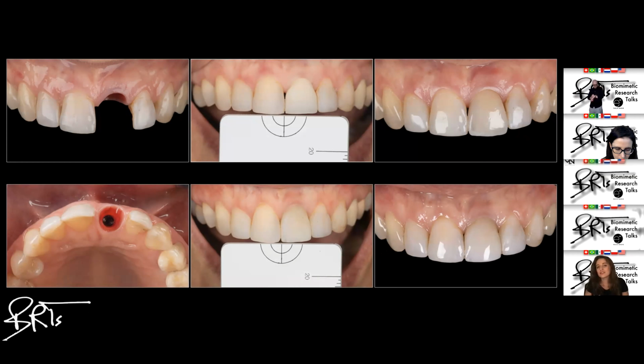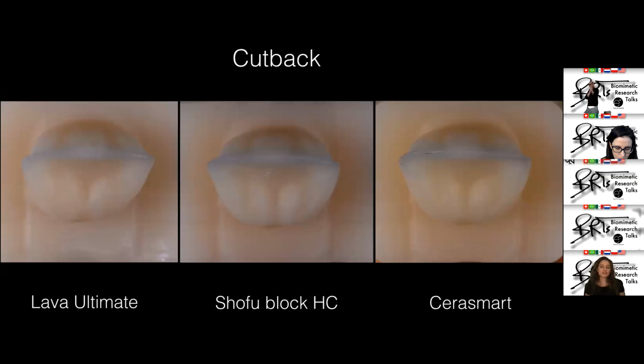So now I want to tell you a little bit and show you a little bit how you can use those CAD/CAM composites in your dental practice and how you can stain them easily so they are more applicable for your use. So our research program with Pascal in the B12 lab included testing a lot of specimens. One group was full contour specimens and two other groups of each of the blocks that you can see on the screen, which was Lava Ultimate by 3M, Shofu Block HC by Shofu, and CeraSmart by GC, where all of the specimens were cut back, and then one group per each of the specimen contained veneered specimens just with the composite on the buccal, and another group contained a layer of stains between the veneering composite and the blocks themselves.